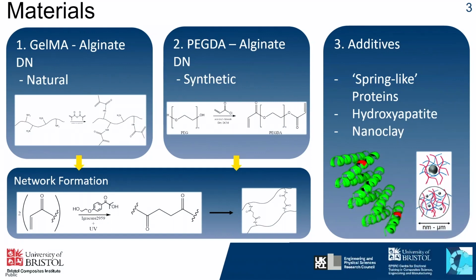Finally, I also look at a range of different additives. I've worked with a master's student designing bespoke spring-like proteins which can be used to absorb the compressive load within the 3D network, and also hydroxyapatite and nanoclay nanoparticles, and they're mainly used to improve the fracture resistance of the materials.